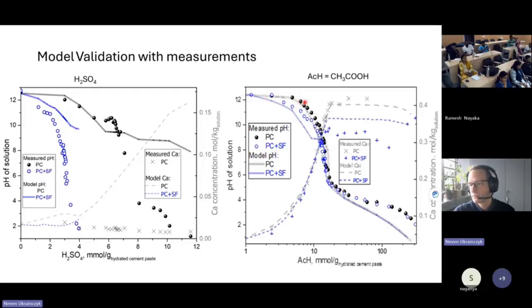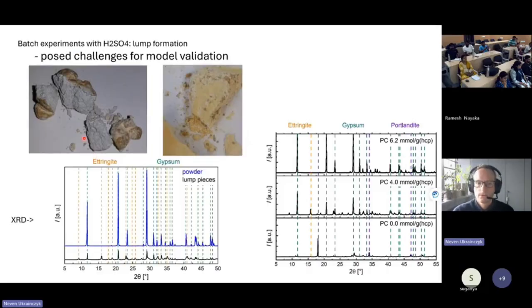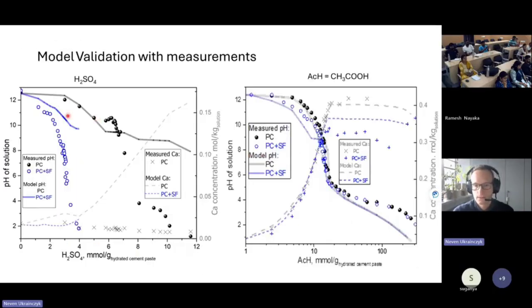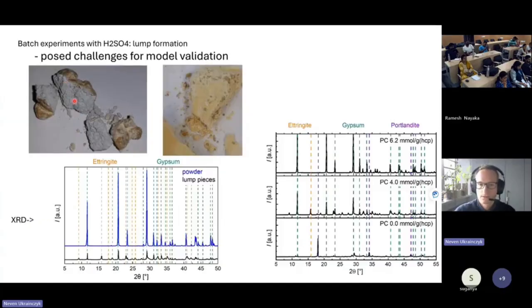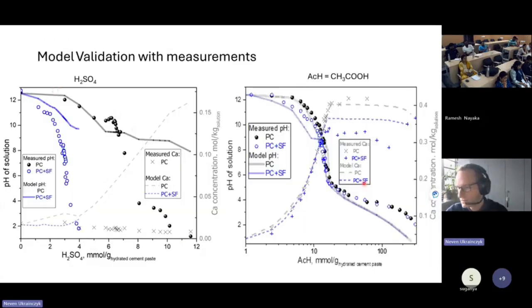So the thermodynamic modeling actually predicts very well the equilibrium concentrations of acetic acid. For the sulfuric acid it was not successful because of this. We could not reach equilibrium because we had this protective layer, and this is why we could not predict here. So this was kinetic control. We wanted to use equilibrium, but there was no equilibrium because there is a lot of cement which was not reacted by acid, was not detected. So this is why we could not predict here. But for acetic acid, actually, it worked very well.